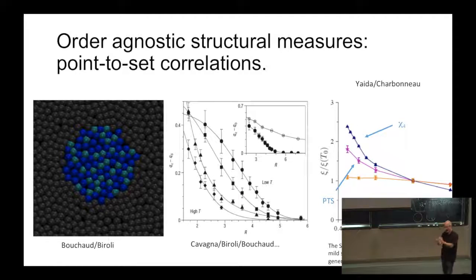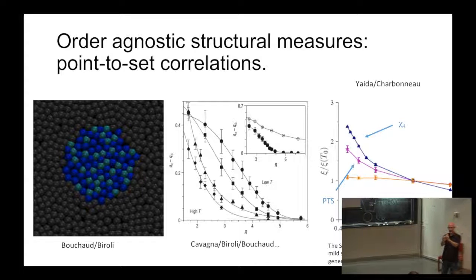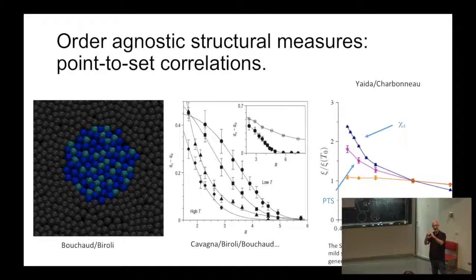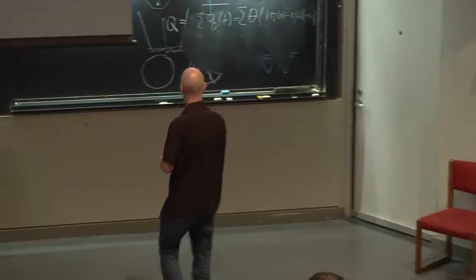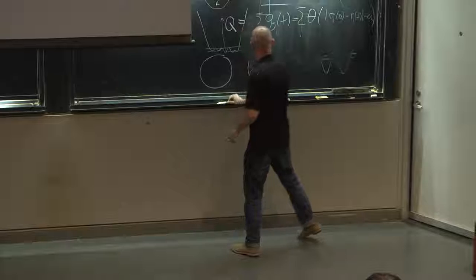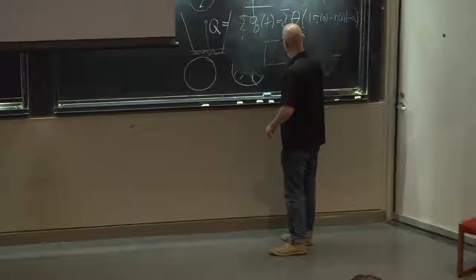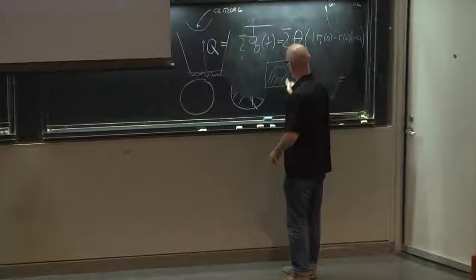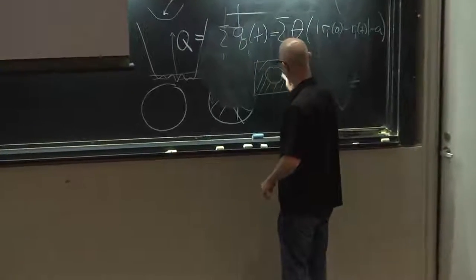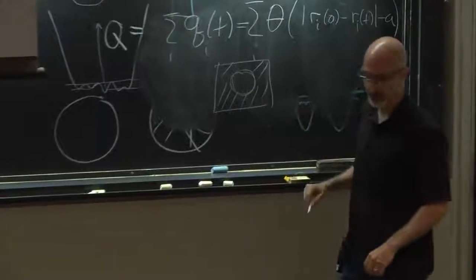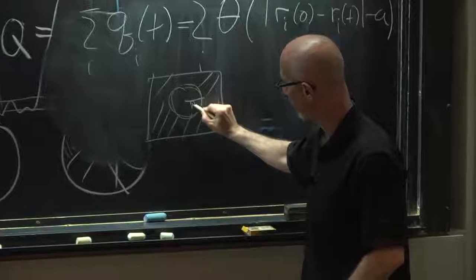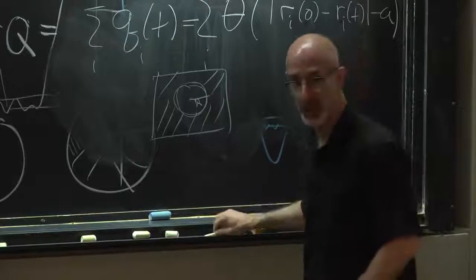And what I can do is ask in a thermodynamic sense, what is the overlap thermodynamically between all of the different configurations inside that sphere that I've sampled. And I have to make sure that I'm not asking a dynamical question. I want to ask a thermodynamic question. So I basically want to ask the conditional probability to have all the particles outside the ball in their same positions, but all the possible different ways I can arrange the particles inside the ball, and that's clearly going to be a function of the size of the ball that I draw.